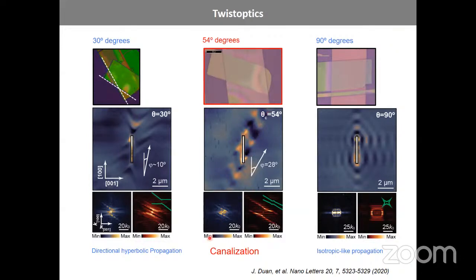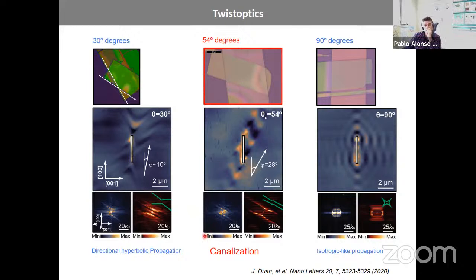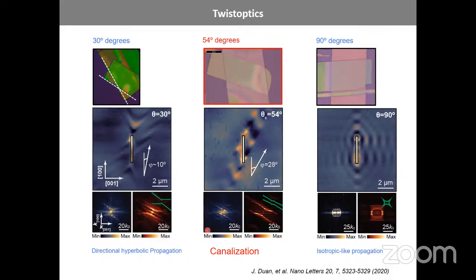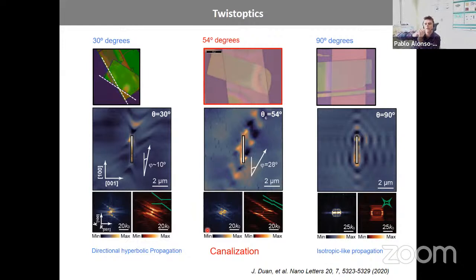So for the context of cavities, that dictates the distance between the two boundaries that would give you the ideal accumulation of energy, right? Yes, that's true. If you have very separated flat bands, you have to make a really small cavity. I see, because you have very small wavelengths. It actually puzzles me that you get into this of cavities with the flat band condition, because it's really something that one needs to think about: how to orient these boundaries, and any angle is possible. And you can imagine, I don't know, a slight defect in the twisted sample that is isolating this part from the rest. It's a cavity. It's a perfect cavity. Right, exactly this case.